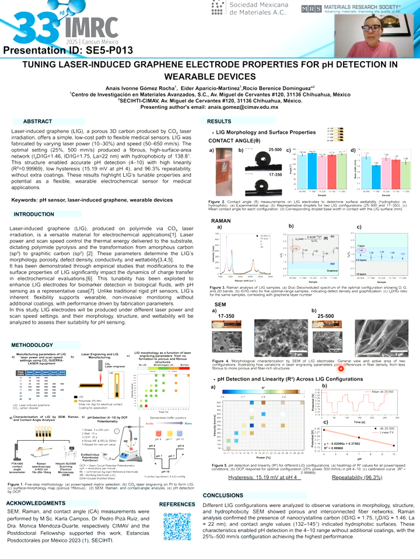Today, I will present our work tuning laser-induced graphene electrode properties for pH detection in wearable devices. For introduction, laser-induced graphene, or LIG, is a carbon material made directly on polyimide using carbon dioxide laser light. By changing two parameters, laser power and scan speed, we control how much heat is applied. This heat changes the material from amorphous carbon to graphene carbons.